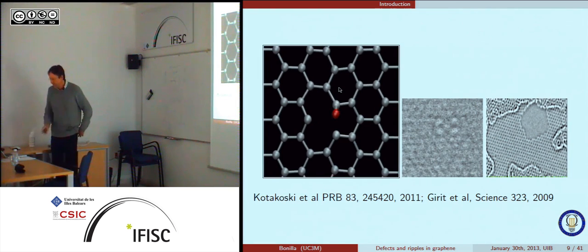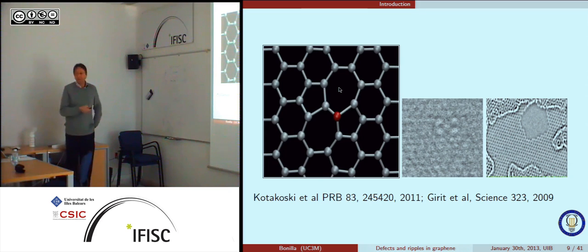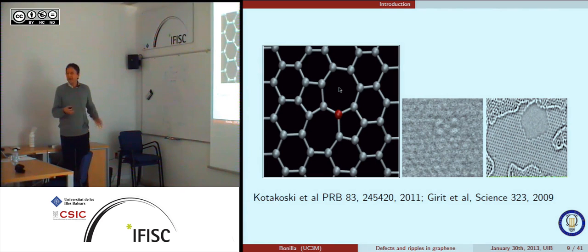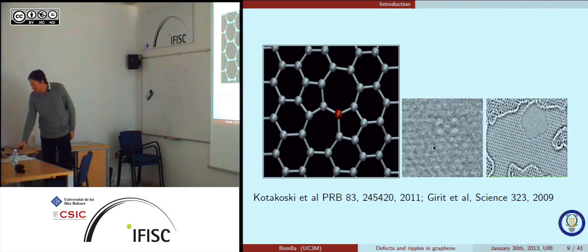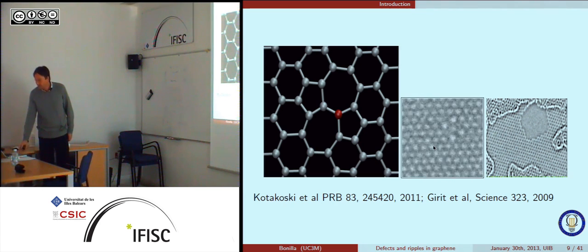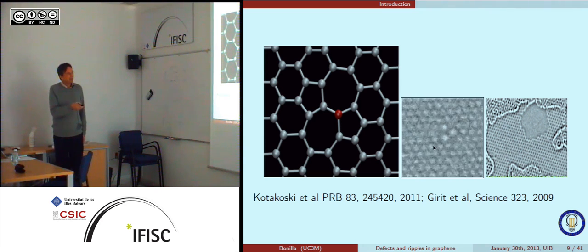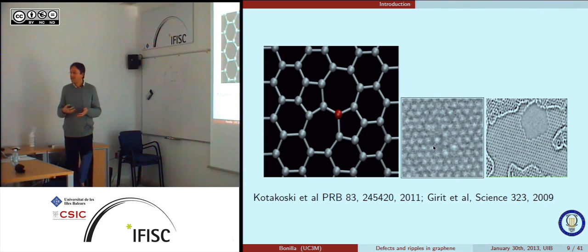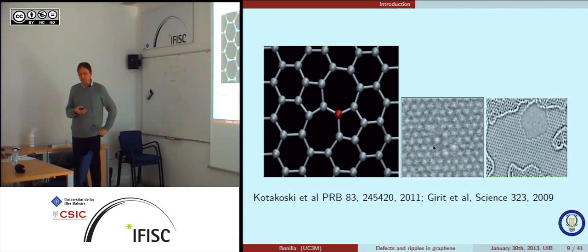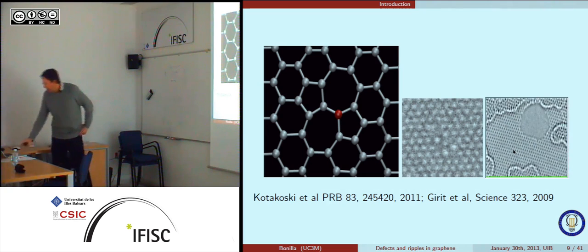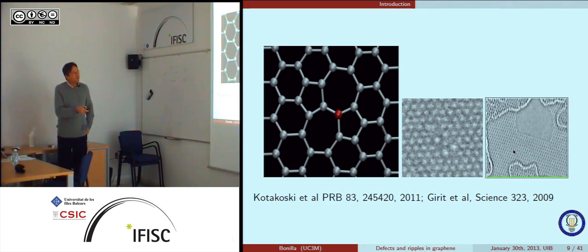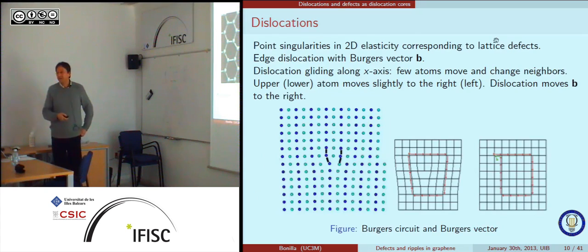Okay, so this is an illustration of how this bond rotation goes. You have the atoms, which are the things that move, and these lines are just put on the shortest distance between atoms. So you see that out of the pristine lattice, you rotate the bond, and you create the two heptagons and the two pentagons. The Stone-Wales defect. These other things are movies, just to illustrate how these things look without the software. Here there is a vacancy, two atoms missing, and in the lattice it is like two pentagons around an octagon. It's a movie of a hole created here, and if you look with care, you'll see some of the defects running around.